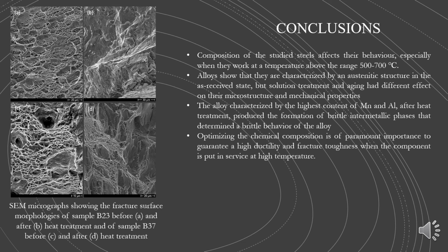Hence, it can be concluded that the composition of the studied steels affects their behavior, especially when they work at a temperature in the range of 500 to 700 degrees Celsius. The alloys are characterized by austenitic structure in the as received state, but solution treatment and aging have different effects on their microstructure and mechanical properties.